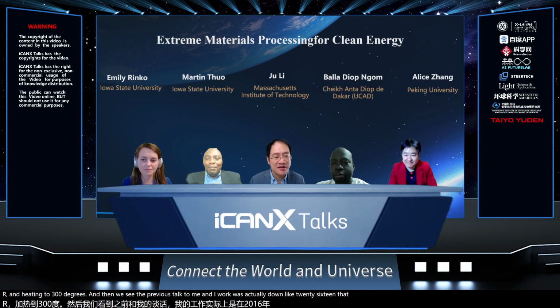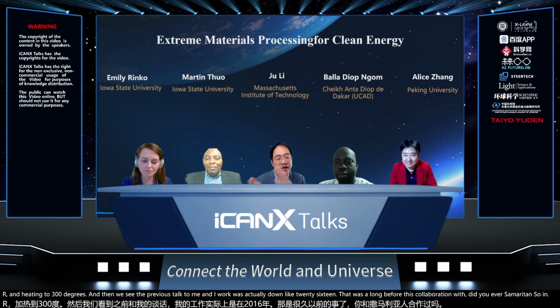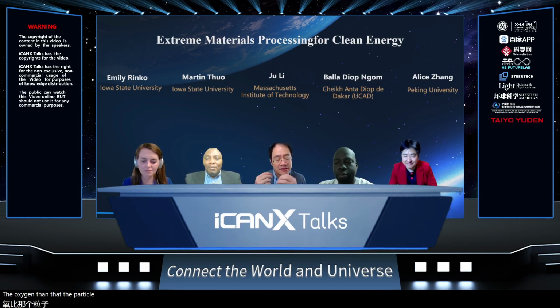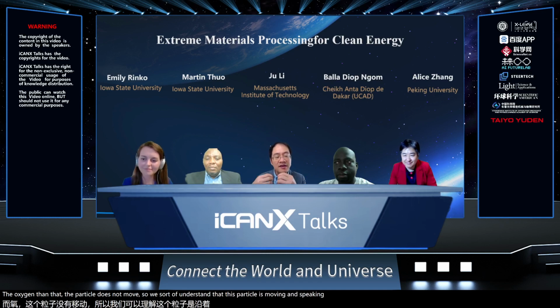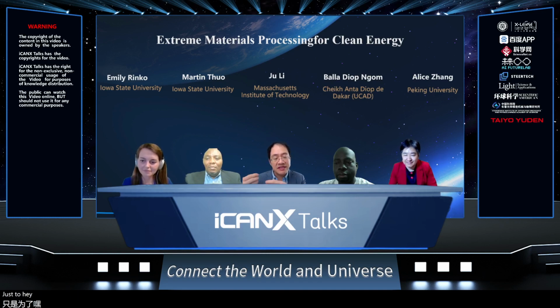And that work was actually done in 2016, long before this collaboration with University of Maryland. In that case, we saw that if we don't have the oxygen, then the particle does not move. So we understand that this particle is moving and splitting basically to catalyze the burning of the hydrocarbon surfactant with atmospheric oxygen.